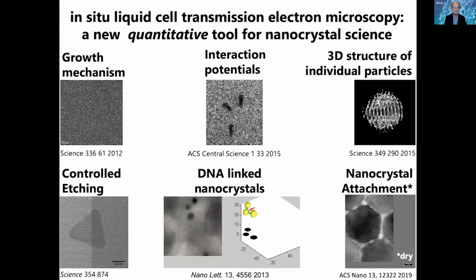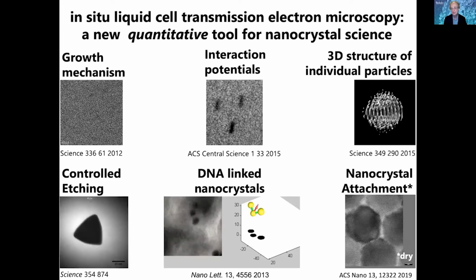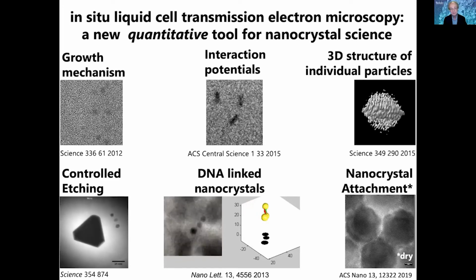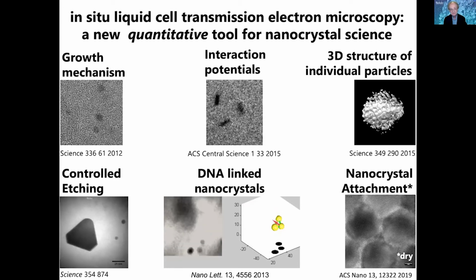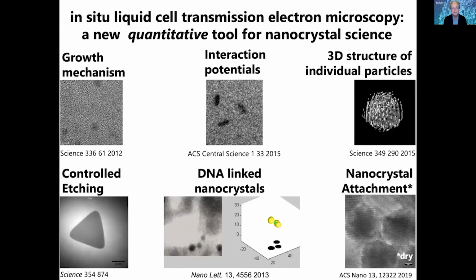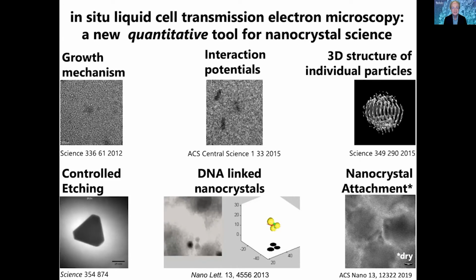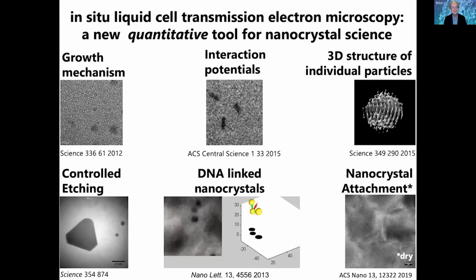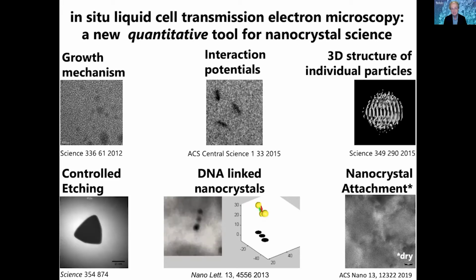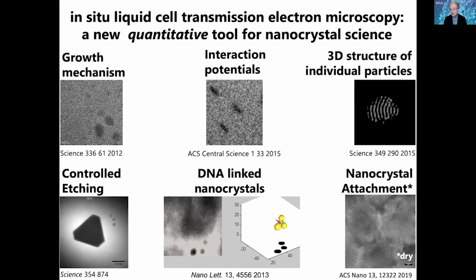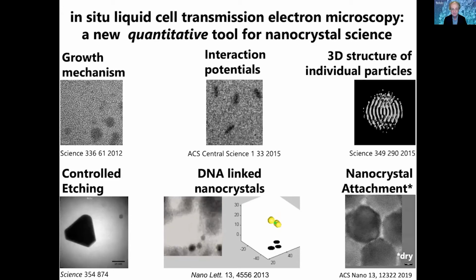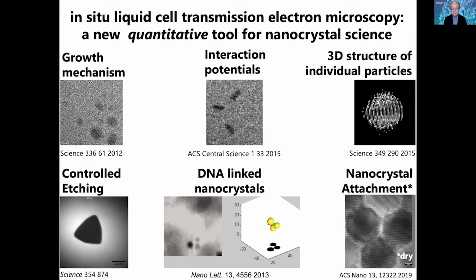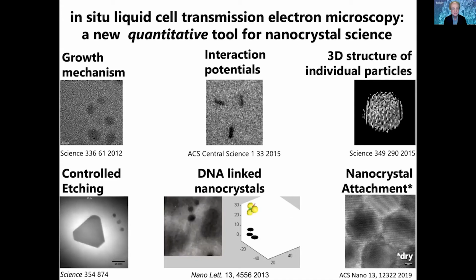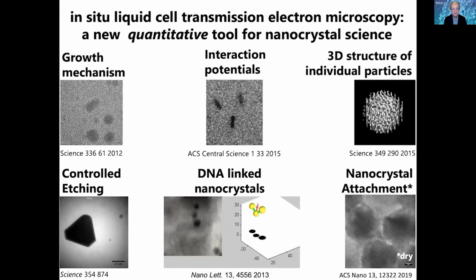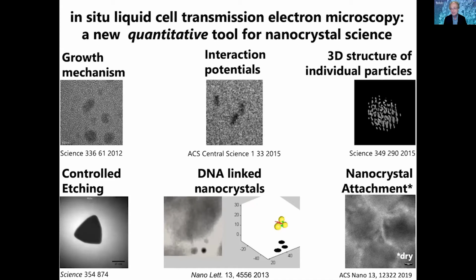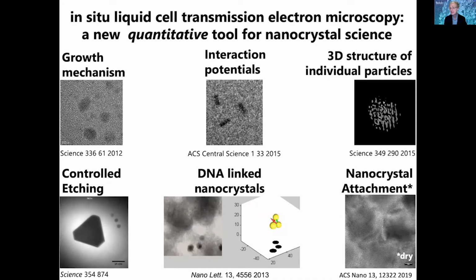In our case, the technique for visualization is one that we have been investigating in my research group since approximately 2007. I believe our first papers were published in 2008. So it's getting to be a while now, 12 years. And during that time, we have been able to create environments where very, very thin layers of liquid are trapped between membranes, which an electron beam can penetrate. And then in that small environment, we can now look at things moving around inside a liquid.